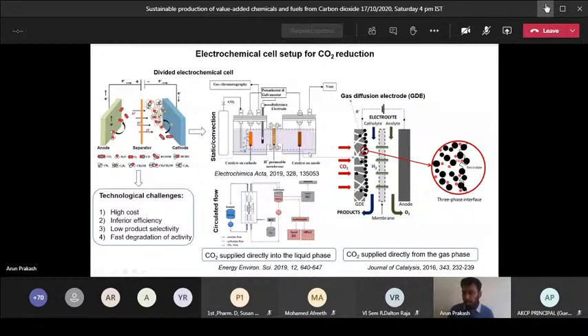In DMF, the solubility of carbon dioxide is almost 20-fold higher than in water. So if you want a better system or better solubility, you can go for a non-aqueous electrolyte. But then you have to choose your reference electrode depending on the electrolyte. If you use a non-aqueous solvent, you have to use a non-aqueous reference electrode.